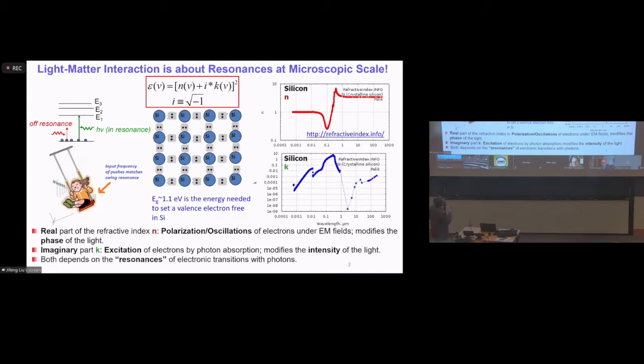So essentially, we have a parameter called refractive index scientifically to describe it. So basically, you probably know the refractive index of water, refractive index of glass. That's the real part of the refractive index. And that's basically talking about how easy it is to polarize the valence electrons in an oscillating electromagnetic field, and how easy it is to oscillate those electrons. So if the valence electrons are weakly bound to atomic cores, they're easier to polarize, essentially to get a higher refractive index. That's why when you go down the periodic table, the refractive index tends to increase.